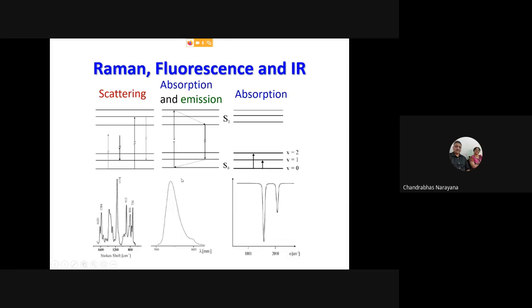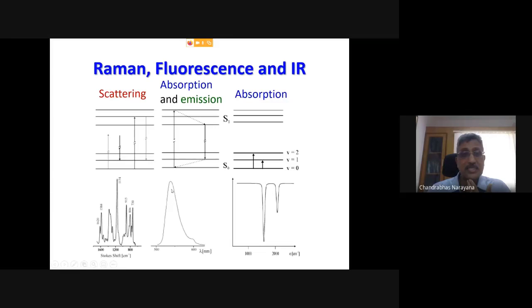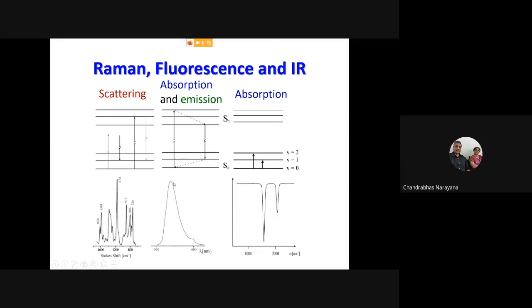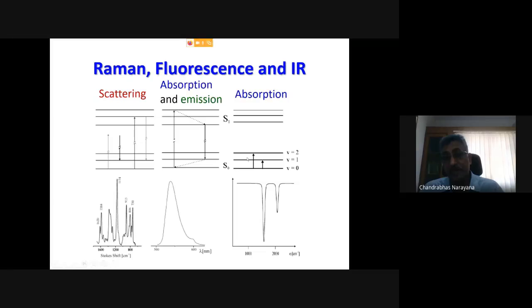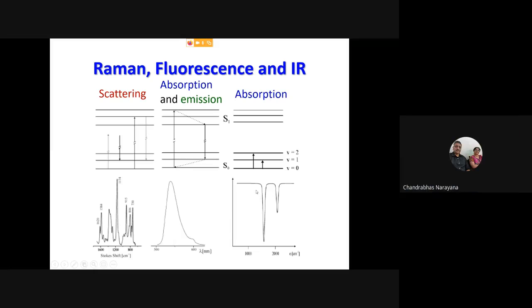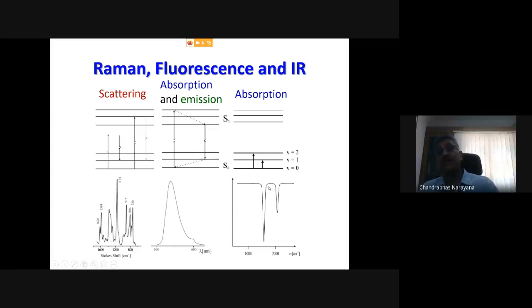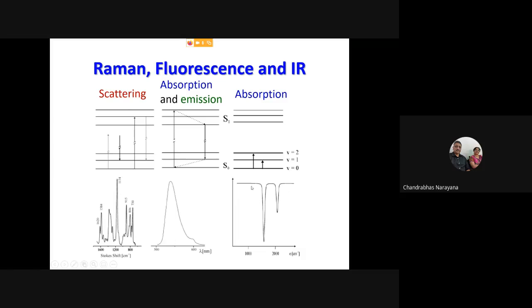You will always have Raman scattering sitting on the vibration, but since the intensity of Raman is very weak compared to the fluorescence, you will not see it unless you zoom up and look very carefully. Whereas infrared absorption is direct absorption. So you only supply the energy equivalent to the vibrational frequency, and these energies are absorbed and removed from the transmission. That removed transmission tells me which energies are absorbed, and that gives me an idea about vibrational spectroscopy. So this is the vibrational spectroscopy relationship.